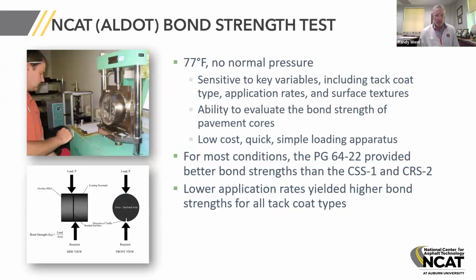So what we ended up recommending after this phase one, the laboratory part of the experiment, was the simplified bond strength procedure. And we picked 77 degrees as the test temperature, primarily out of convenience. It's easy to test at that temperature. We also selected to use no normal pressure, no normal force. So you just put the specimen into the shear device and you go with it. At that temperature, and even with no normal pressure, the test is sensitive to the key variables, including the tack coat type, the application rate, surface texture of the mixes, and so forth. This is really convenient and gives us the ability to test the bond strength of cores.